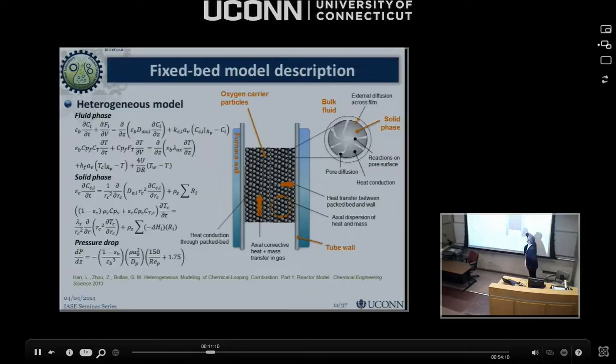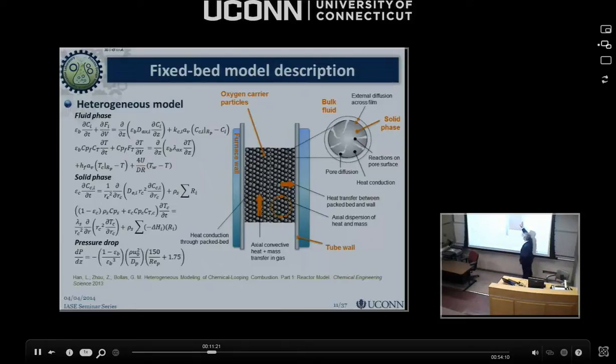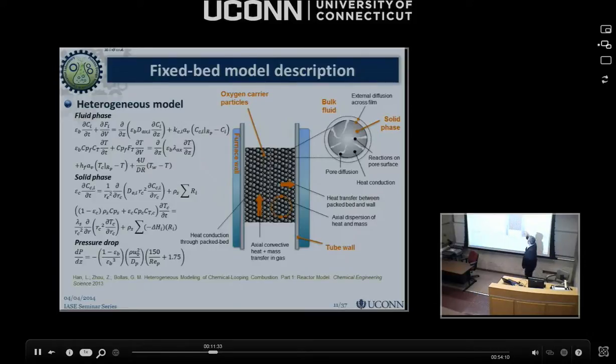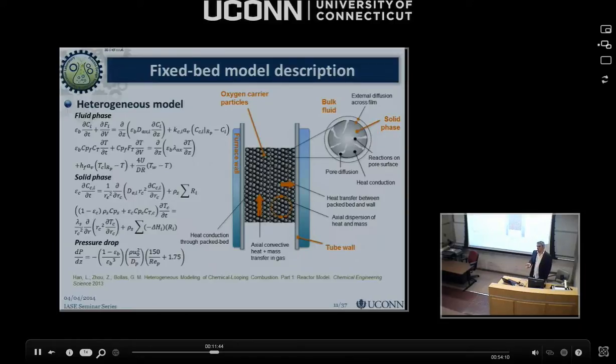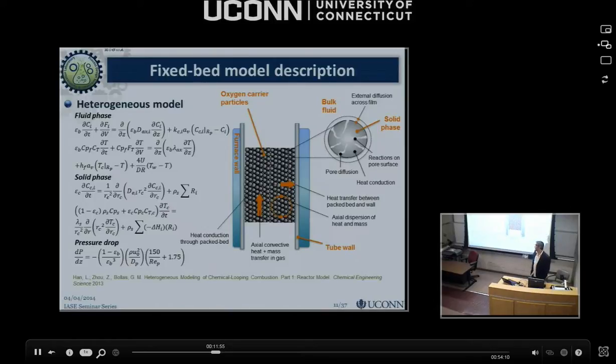We started with a fixed-bed model — it's a standard heterogeneous model where we simulate the fluid phase, the solid phase, and the pressure drop. We assume a constant temperature at the wall and heat transfer from the wall due to exothermic or endothermic reactions, using data from standard fixed-bed reactors published in the literature housed inside a furnace. We take into account all the diffusion effects inside the small particle. What chemical looping uses is what we call an oxygen carrier — that is the metal being oxidized and reduced in every step. The properties of that change over time. We have shown that for relatively larger particles, diffusion limitations in chemical looping are significant and have to be taken into account.